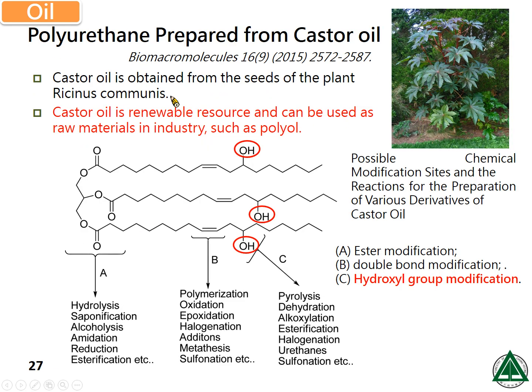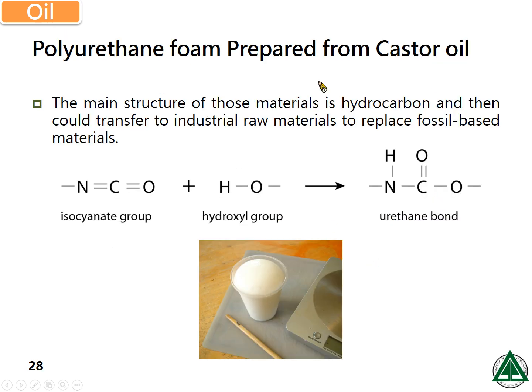It can also be prepared from castor oil. Castor oil is contained in the seed. As you can see, this tree can actually also be grown in Taiwan. Castor oil is a renewable resource and can be used as raw material in industry. Actually, the structure is also like a polyol, so we can use it directly. Moreover, some research also indicates they can use other modification ways to prepare a new polyol. So polyurethane foam can be prepared from castor oil directly because it already contains some hydroxyl groups, so it can react with isocyanate and form the urethane bond.